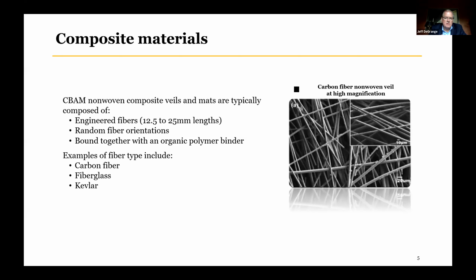But that's basically the build material, these different non-woven fiber sheets. And what I want to highlight with what makes these sheets so unique is we can get them in different fiber lengths. The two different types of sheets that we're working with have 12 and a half to 25 millimeter fiber lengths. They are non-woven, so they do have a random dispersion, but that's where we're going to get our strength properties, with these longer fibers in these sheets. So a lot of different options as far as different feedstock that you can run with the fiber sheets in the CBAM process.